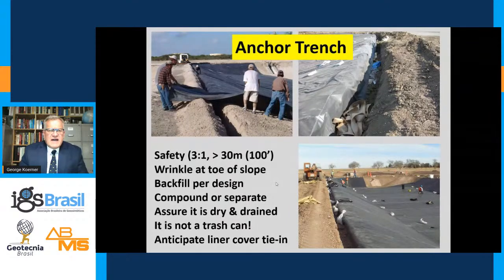If you do not tie off or backfill the anchor trench, you could have issues with wrinkling or caterpillaring of the geosynthetic downslope. You should backfill this per the design, and please don't use the anchor trench as a trash can. This is absurd when you see a lot of different materials, even spent sandbags in the anchor trench. This all has to be removed and taken care of in a very diligent way, obviously not to pollute the environment. You should assure that the anchor trench is dry and is drained.